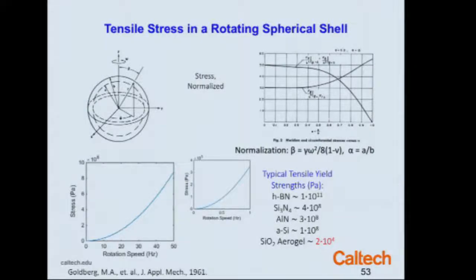So we decided to make an analysis, say, assume we had a structure the size of a light sail that was, say, a disk or a sphere. What rotational speed could it get to before the material at the edge of the sail exceeded the tensile yield stress of the material? And so here are some typical tensile yield stresses for boron nitride, silicon nitride, aluminum nitride, amorphous silicon, and so forth, in the range of 10 to the 8 to 10 to the 11 pascals. And so that basically tells you I could tolerate rotation of the sail up to, for the diameters we're talking about, a few square meters, up to a few tens of hertz or so. You wouldn't want it to rotate faster than that for fear that you would compromise the tensile strength. At least that's my picture of this.